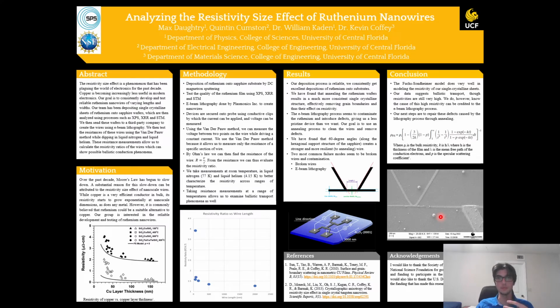Not necessarily having defects or anything like that, but wires that we're just not able to measure. Contamination can also lead to that. If we have a big splotch of something right here, which did happen, it can definitely mess with our measurements and not get us anything useful. The broken wires can most likely be attributed to general handling, exposure to the environment, and possible electrostatic discharge, but we try to do everything we can to reduce those factors. And the contamination seems to mostly come from the e-beam lithography process, which we're working on getting sorted out.